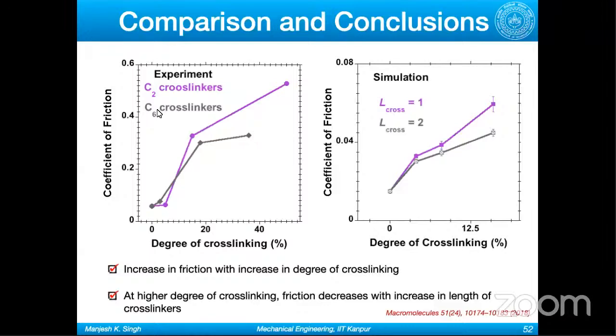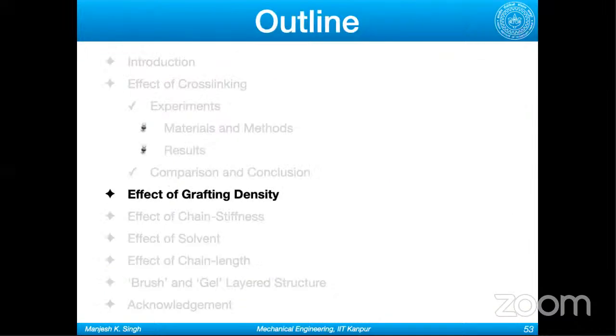But as you increase the length of cross-linker, your coefficient of friction is going down. In simulation, it was very clear and consistent. But in the case of experiments, the effect of the length of cross-linker towards the lower degree of cross-linking is not very clear. And don't compare these numbers of coefficient of friction on both sides, because the idea was not to make a quantitative comparison, since I was doing the simulation in reduced units. It was not all-atom simulation, it was more on the physics side. So we are basically comparing the qualitative trends which we see in simulation and experiments. With this, I'll move to the effect of grafting density.